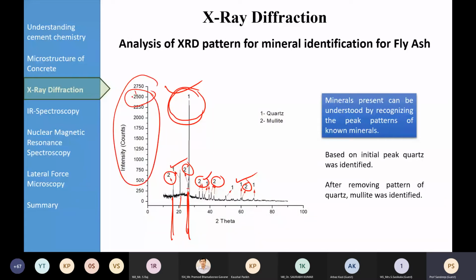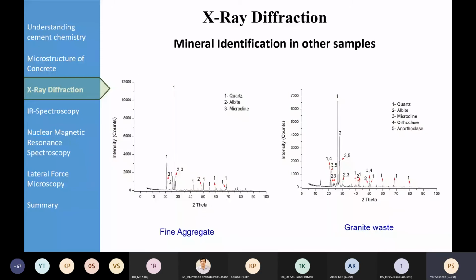So that should be understood. So minerals present can be understood by recognizing the peak patterns of known minerals. And based on initial peak, quartz is identified here. And after removing the pattern of quartz, once you remove that, then you can identify the mullite. So this is the manner in which you need to do the XRD analysis. Like here, this is mineral identification in other samples like quartz, albite, microcline. So you are able to see the quartz, you are able to see albite, and you are able to see